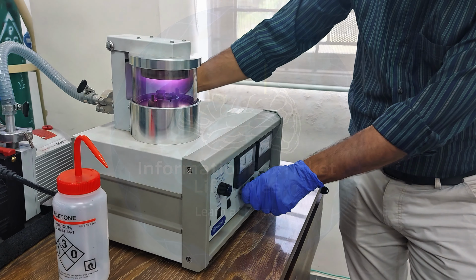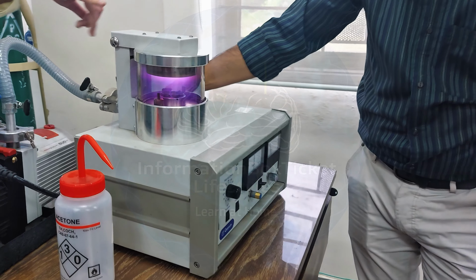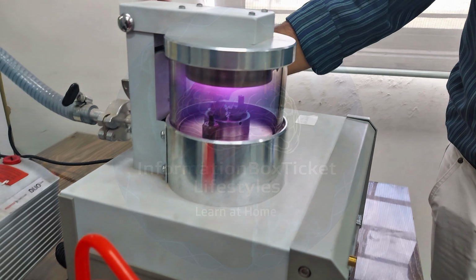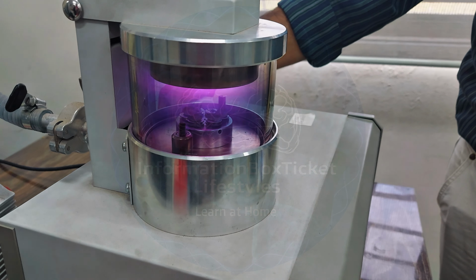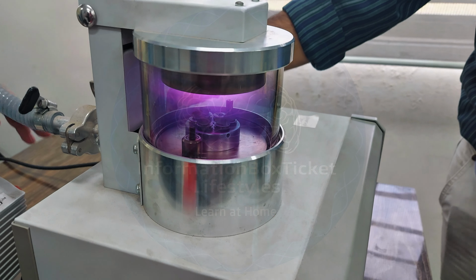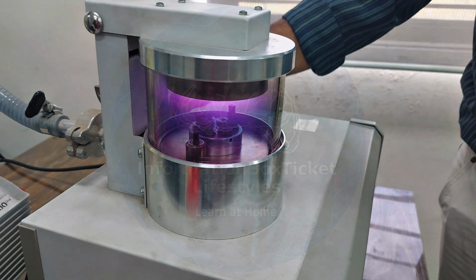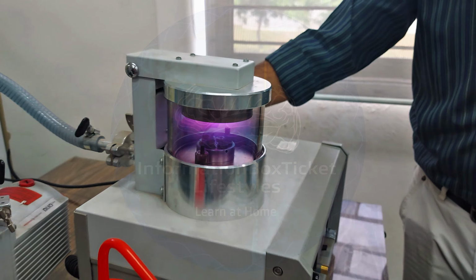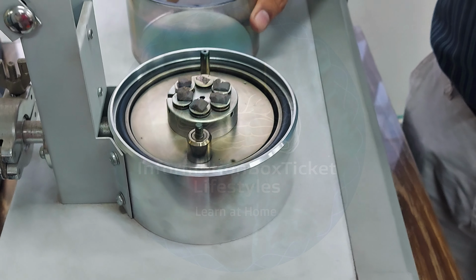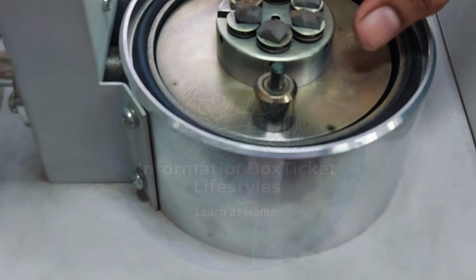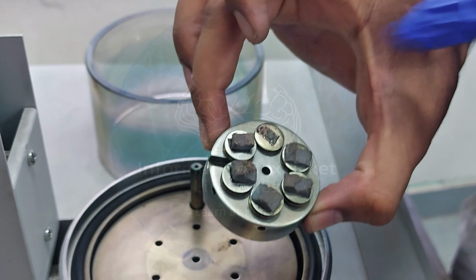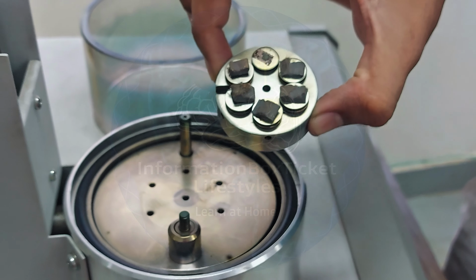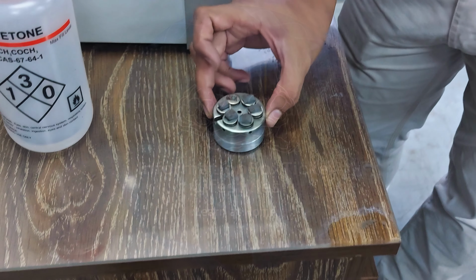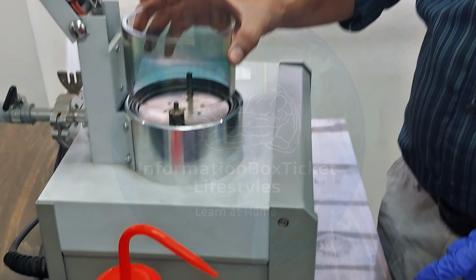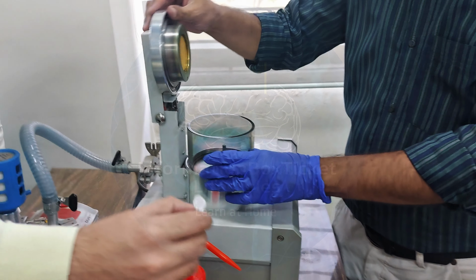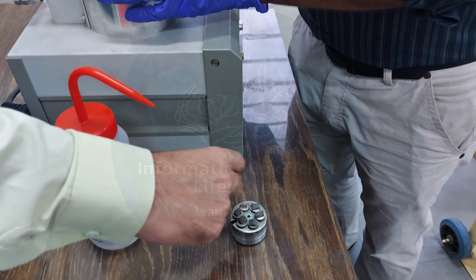After the required vacuum level is achieved, argon gas is introduced, plasma is generated, and sputtering begins, depositing a thin, conductive coating onto the sample surface. Notice how the sample appearance changes from golden to gray. This occurs because the deposited metal layer is extremely thin and uniformly spreads over the surface, altering its reflectance.